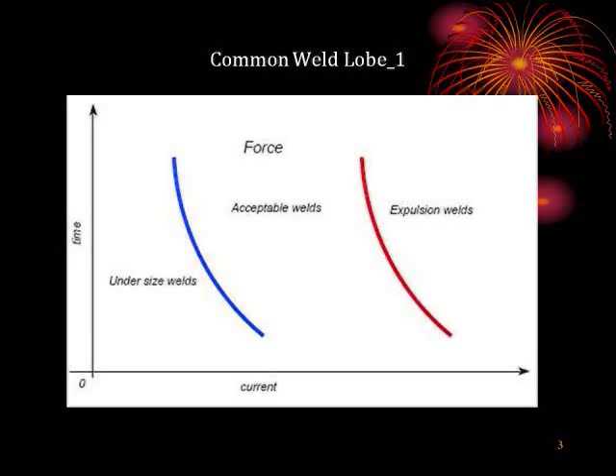This diagram, the weld lobe diagram, has the x-axis as the current and the y-axis as the weld time. And this weld lobe has two curves. On the left hand side is a blue curve. The right hand side is a red curve. The blue curve separates the acceptable weld from undersized weld or no weld. The red curve separates the acceptable weld from expulsion welds. And the whole thing is found experimentally, done under a fixed force.